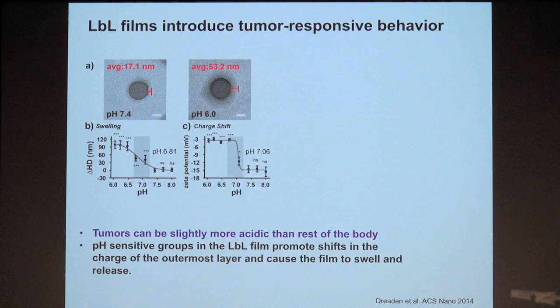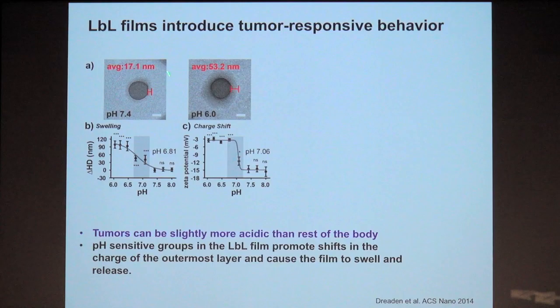depending on the degree of acidity that tumor expresses. What we were learning in generating our layer-by-layer films is that when we introduce positively and negatively charged polymers that can respond to pH with a shift in charge, we can actually design systems that undergo a change in net charge when we shift the pH of the tumor. So here's a nanoparticle at pH 7.4. It has a dense, very hydrated layer that's about 17 nanometers thick, and you can actually see it, hopefully, this little halo. When it goes down to very low pHs, we get a lot of swelling.